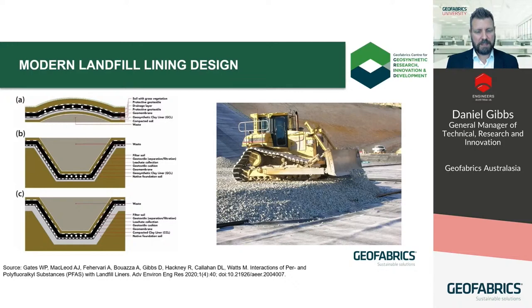What happens if the geomembrane has a defect or a hole? Then diffusive flux gives way to advective flux, and we now need to understand how liquids containing PFAS interact when in direct contact with the GCL components in terms of the impact on hydraulic performance and whether or not these chemicals are trapped in the bentonite, which has a history of being generally pretty good at trapping certain contaminants like heavy metals.